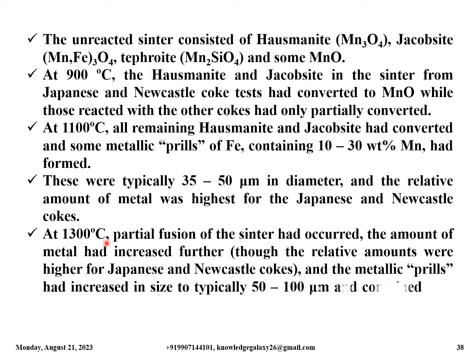At 1300 degrees Celsius, partial fusion of the sinter had occurred. The amount of metal had increased further, though the relative amounts were higher for Japanese and Newcastle cokes, and the metallic prills had increased in size to typically 50 to 100 micrometer and contained 30 to 40 weight% manganese. Now let us discuss changes in coke properties.